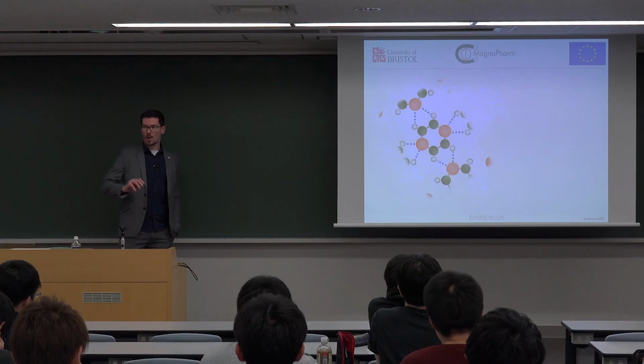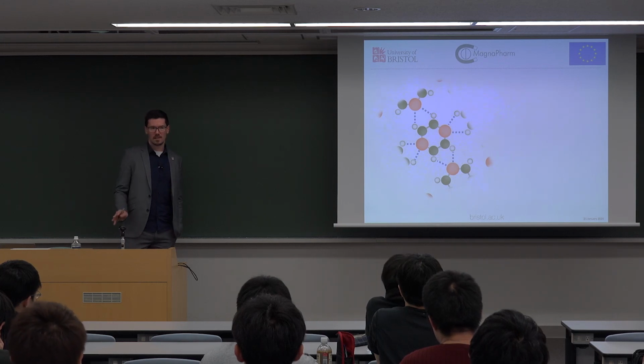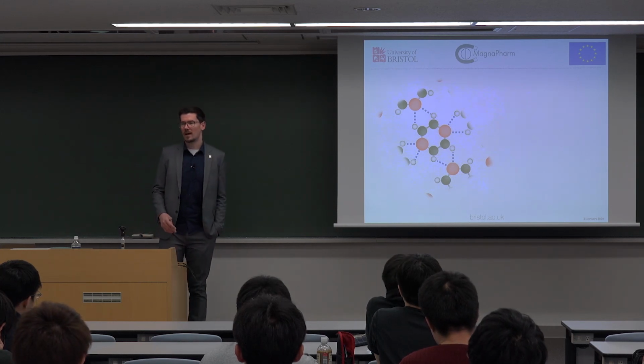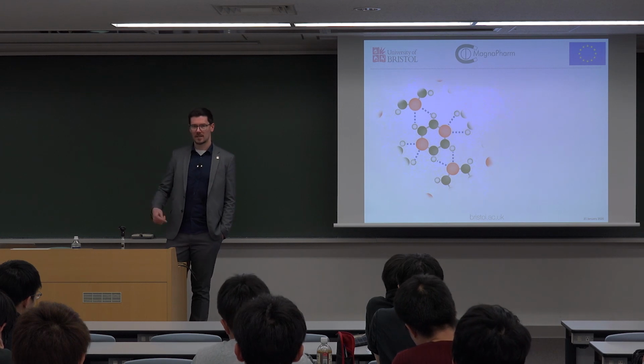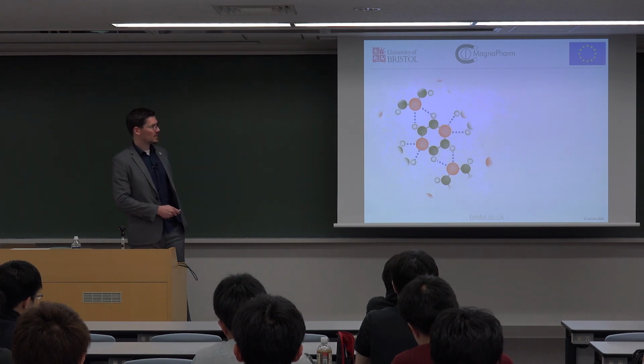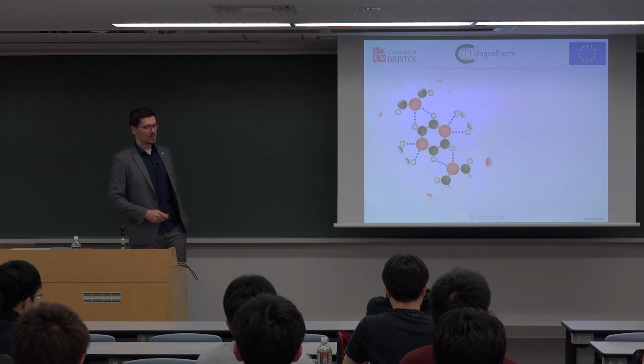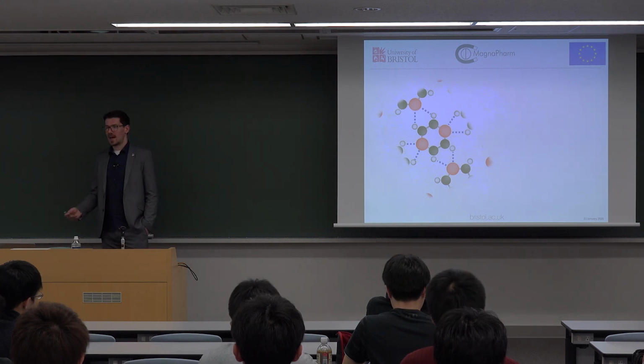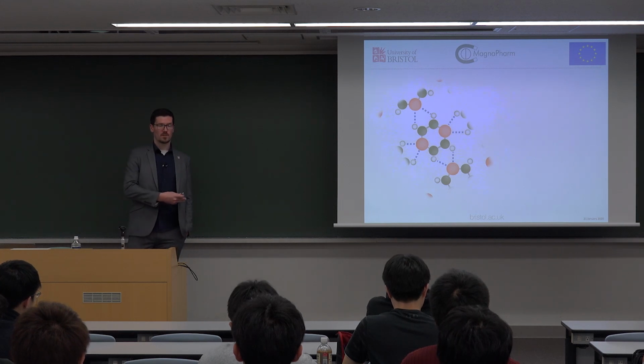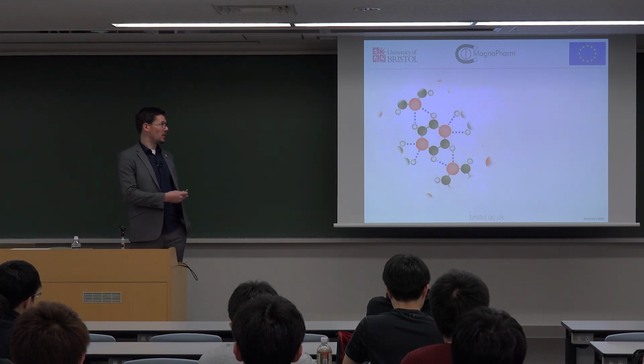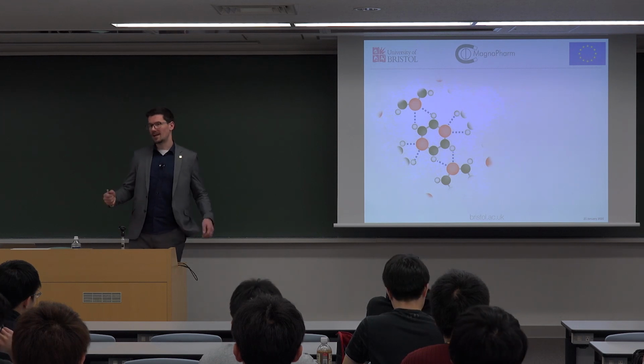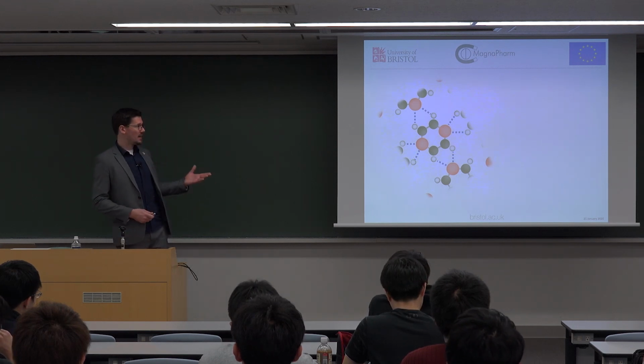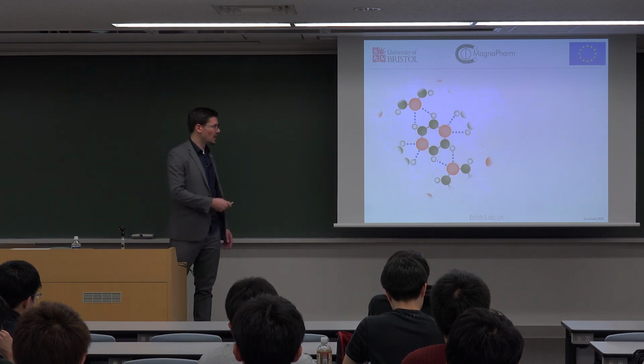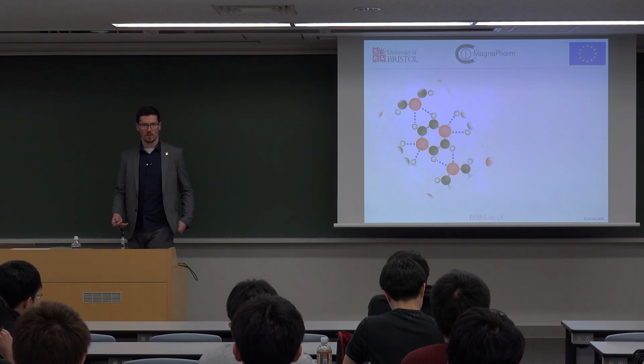So if we look at one closely in that arrangement, you start to understand that the bulk properties of the material that the molecular solid makes are a function of how each molecule interacts with its nearest neighbor. So here we can see that the red atom is interacting with the 2 white atoms. So that is going to be the dominant intermolecular force in this crystal. So if those bond interactions are fairly weak, then we're going to have a very soft material. If they're very polar, if there are induced dipoles there, then maybe it will be very soluble in water.